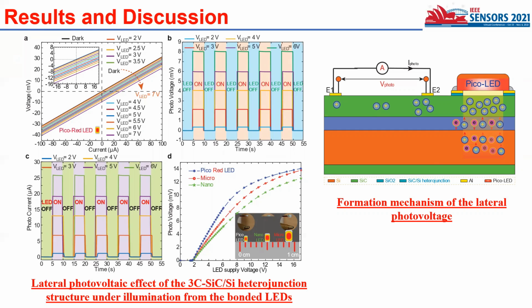So the formation of the lateral photovoltaic effect is a combination of the electron-hole pairs generated under the LED illumination, the injection of the holes into the silicon carbide, and the diffusion of the holes in the silicon carbide layer, which creates the gradient of the carrier concentration on the top of the silicon carbide layer.